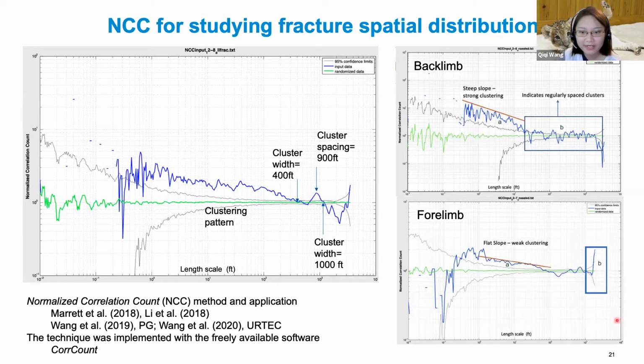Also, if you look at the right-hand side, the two plots, the higher elevation and the steep slope of this plateau of the blue line indicates a higher degree of clustering in the analyzed data set. So the key finding here is that the gently dipping backlimb of our asymmetric anticline is showing a higher degree of fracture clustering revealed by the steeper slope of the blue line. And this is in general the truth among all the studied wells. And we also found despite the higher fracture density, the fractures at the forelimb are the least clustered.